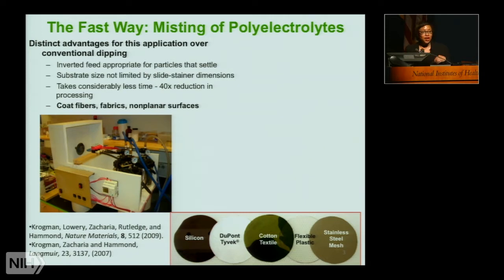But even in that process, it can take anywhere from a few minutes to 15 or 20 minutes for each absorption step, which is wonderful for lab, but isn't great for manufacturing. However, this is a very scalable process because you can actually use other methods. And here we're showing one method, which is spray layer by layer, that was an automated form which was generated in our laboratory, in which you can use convection to spray dilute concentrations of these different systems onto a substrate directly, spray the rinse, and then spray the other system.